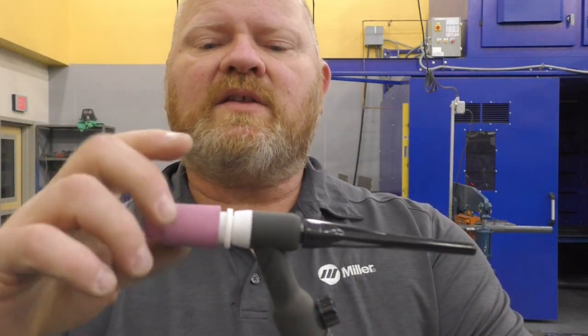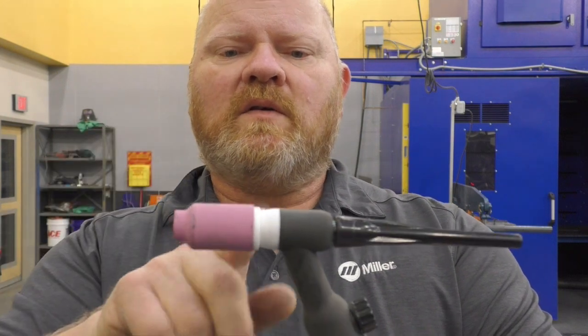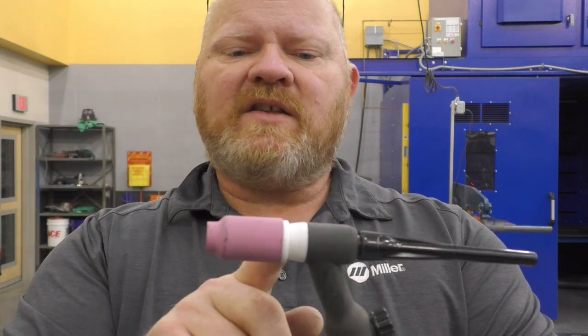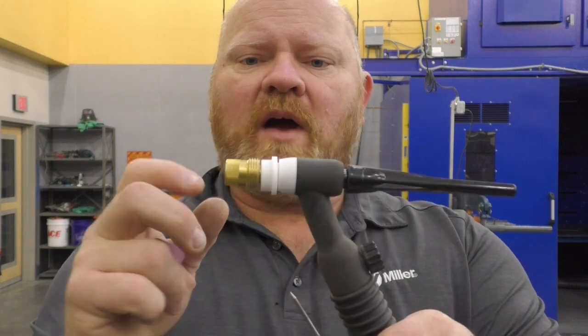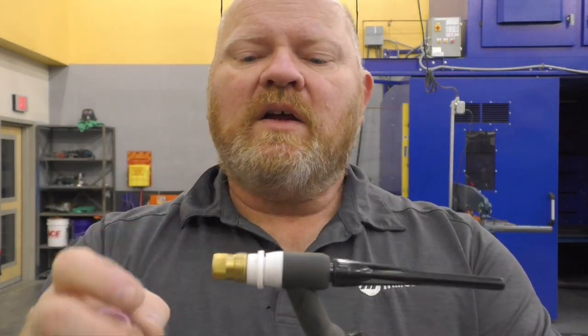This cup, when this threads on, it needs to bottom out on the back end of the cup. If that spacer is not in there, or these parts aren't installed correctly so that the back end is pushed in too much and the front end is sticking out too far, the cup will rest on the front end here. It will bottom out on that shoulder. When that happens, and especially if you're walking the cup, the technique that is most preferred by people in the TIG world, the cup will tighten down on that shoulder. As it gets hot, it will expand. It is ceramic, but it still expands.